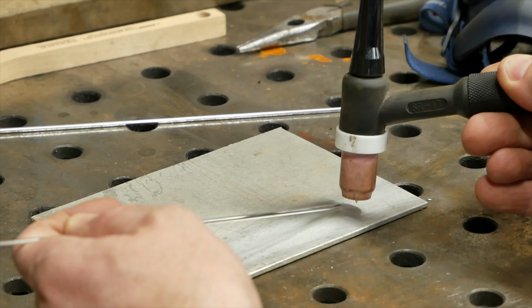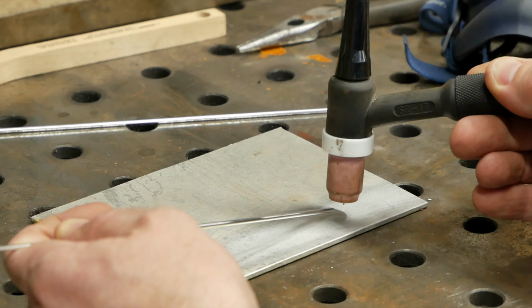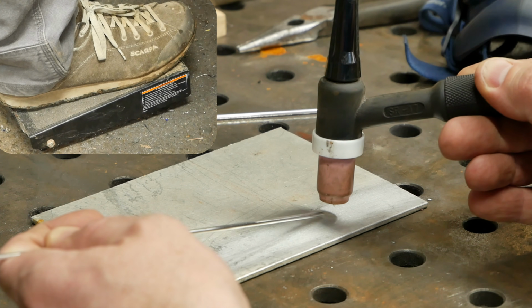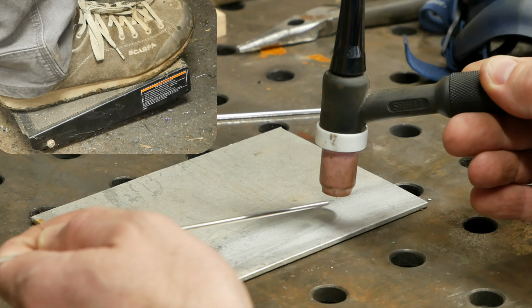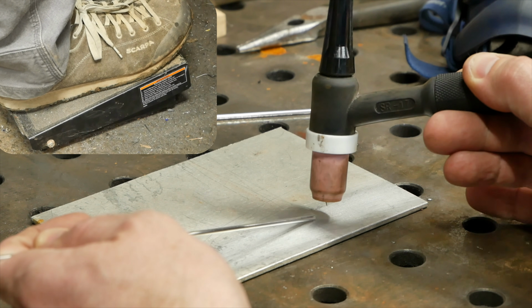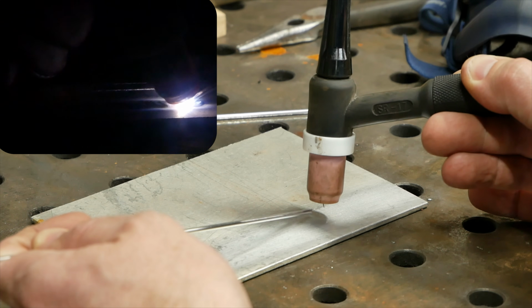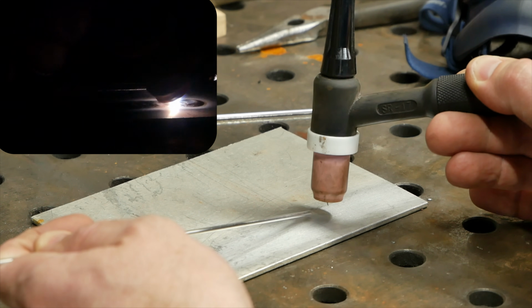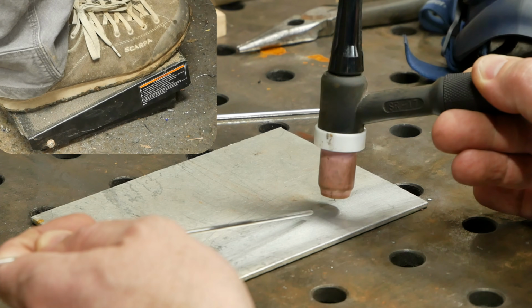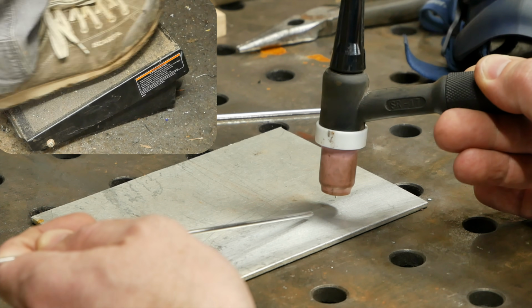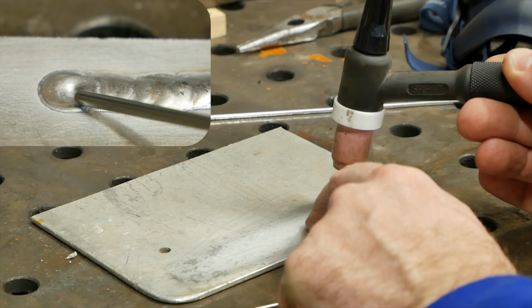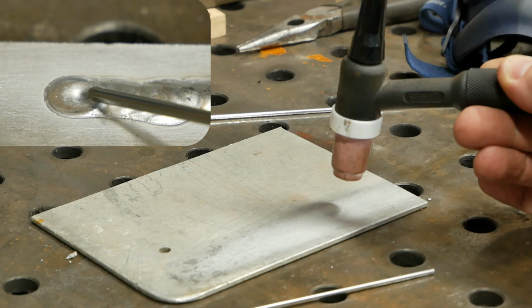Every time you dip the filler rod, it will actually cool the puddle slightly. If the puddle is getting really wide and hot, looking like it's melting through, you'll want to ease off on your amp pedal a little bit. And then once you get to the end of your joint, you'll want to ease off a little bit, put a little bit more filler rod in there, roll your amps way down and back up over the joint a tiny bit, and then drop off the pedal 100% so it shuts off. Adding that little bit of filler rod at the very end and easing off your amps will help the joint not get a kind of a dimple or a pocket or a weak spot there.